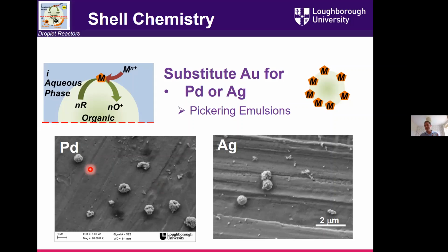Now the solvent has gone. You can see it resembles something that might have come from a droplet. And in my mind, I thought, well, maybe this is something like a Pickering emulsion. We've made metal particles on the outside of the droplet. We've removed the solvent, and we can see the final material. And we got something for silver, and we got something for palladium. We thought, wow, fantastic, let's press on and keep going with this.